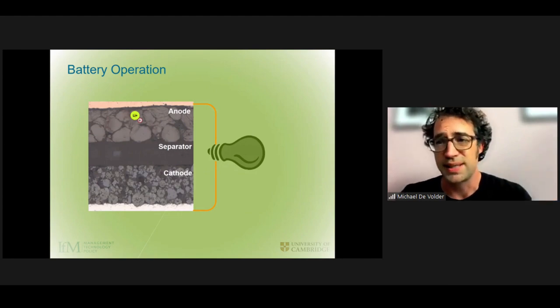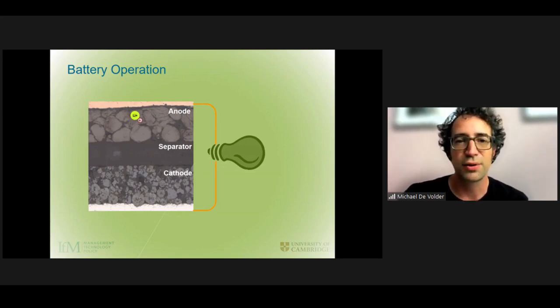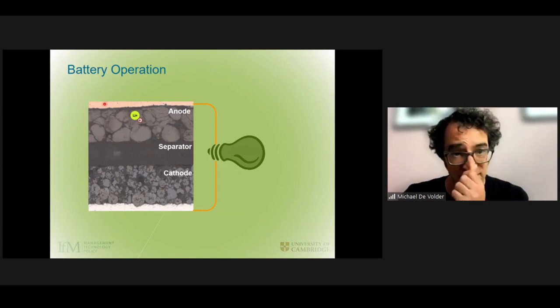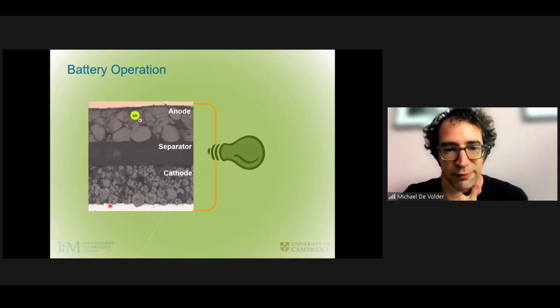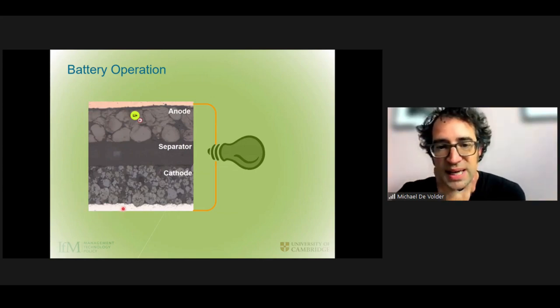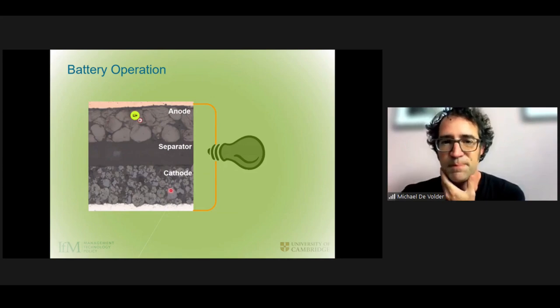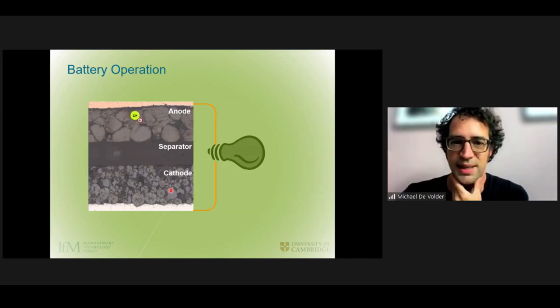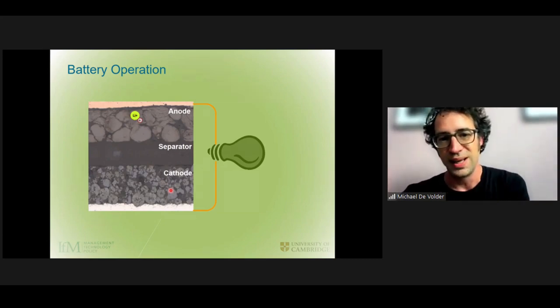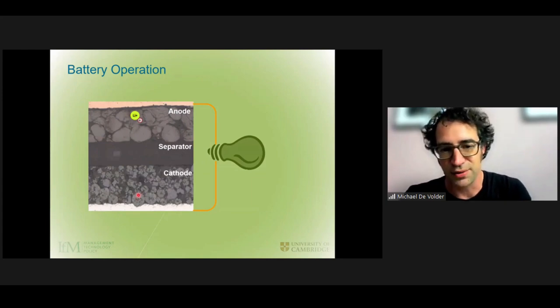So in essence, it's quite simple. It consists of an alternating stack of anode and cathode materials that are coated on metal foils. So a copper foil at the top on the anode and an aluminum foil on which the cathode material is coated on the bottom of this slide. And what happens when you charge your batteries is that you're going to pull lithium ions from the cathode, so the particles at the bottom here, and store the lithium ions in the anode.